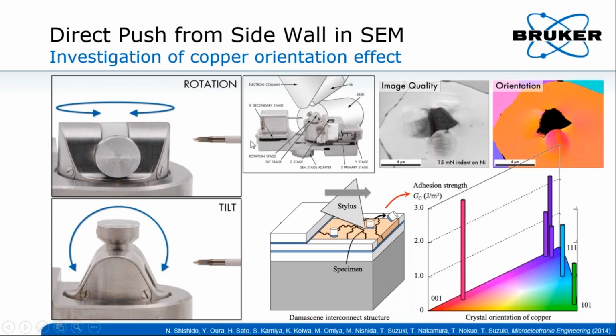First of all, we move the sample to the FIB gun to create the micropillars, and then move the pillars to the probe for direct push from the side wall. Finally, move the sample surface to the EBSD gun for orientation measurements. Therefore, it is so smart and so efficient to get all necessary measurements done in one SEM chamber.